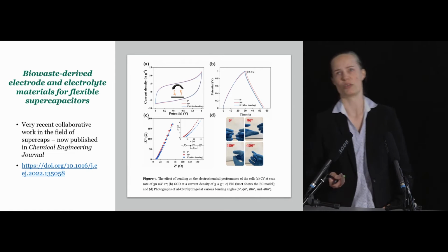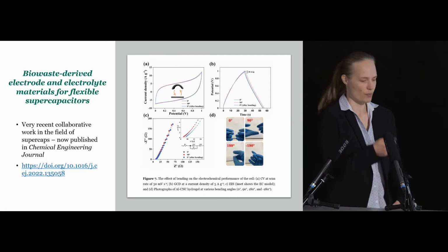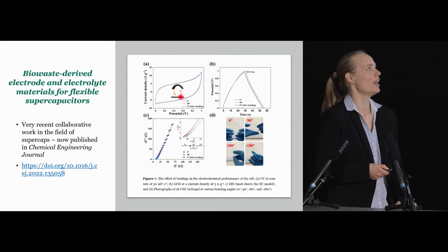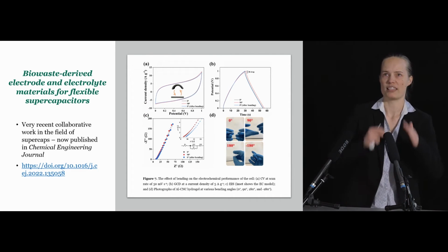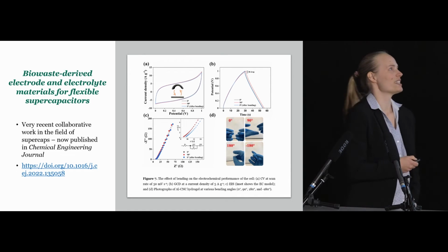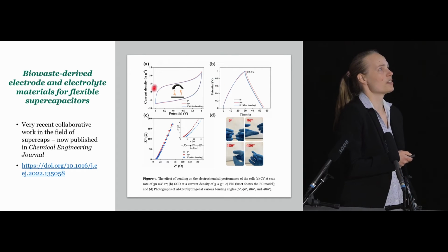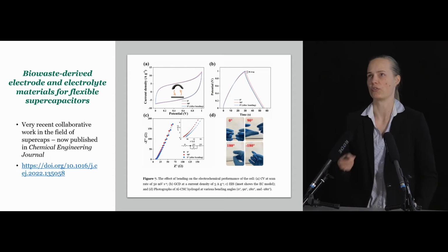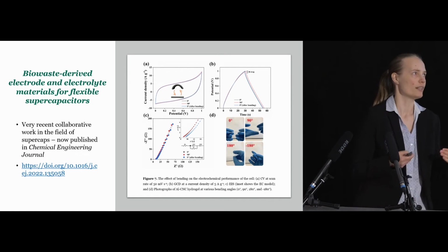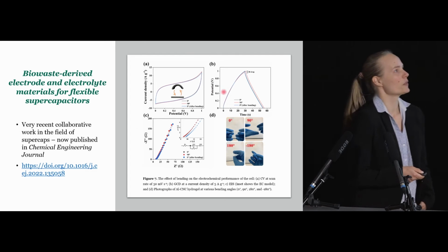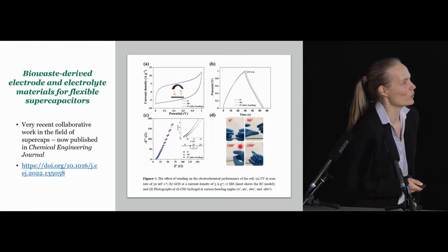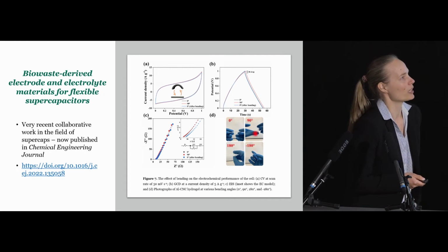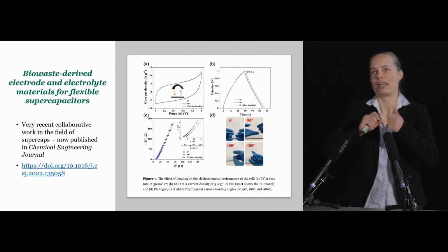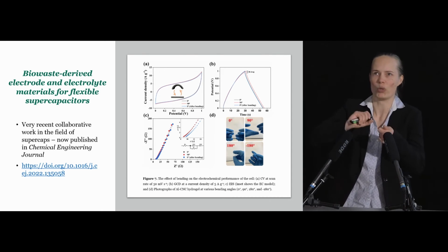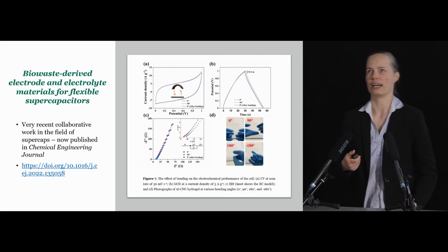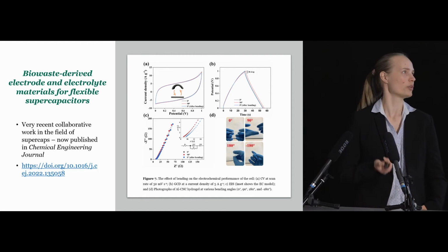Okay, it's a long process with a lot of electrochemistry involved, but I'm going to cut some corners and just highlight one of the final results. What was great here is that if you bend these supercapacitors to 90 degrees, you can see here that it almost doesn't have any impact on the performance of the device. So they are quite highly bendable. And also here, I know the contrast is not the best, but you can see how well you can manipulate these gels, so you can really twist and roll them, and they hold together very well.